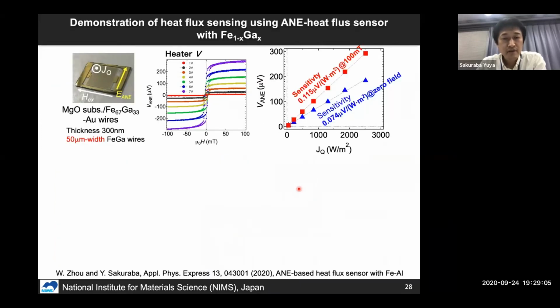Okay, so we measured the magnetic field dependence of the output voltage of this prototype heat flux sensor. This is a result of the heat flux sensor made on the MgO substrate. The width of the iron gallium is 50 micrometers in this device. As you can see, the output voltage of the Nernst effect increases with increasing the input voltage to the heater. And here you can see the heat flux dependence of the anomalous Nernst effect measured with and without an external magnetic field. In both cases, we can clearly see a linear dependence of the anomalous Nernst voltage as a function of heat flux. So this result clearly indicates the anomalous Nernst effect can be used as a heat flux sensor even without an external magnetic field.